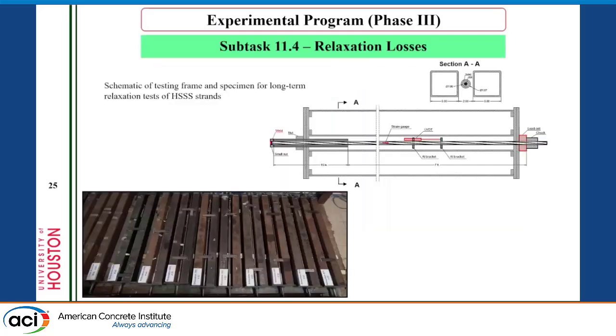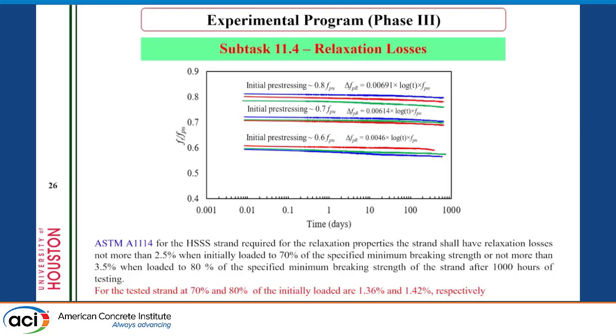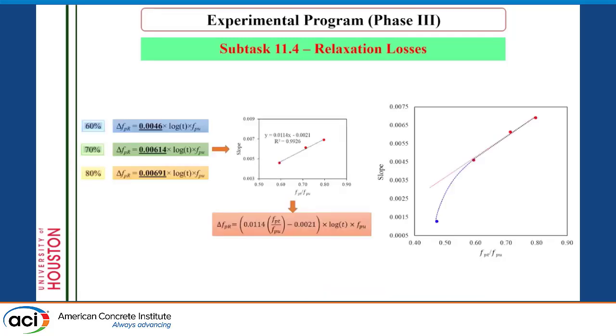Another topic is the relaxation. The same thing: we have to measure the relaxation to measure the losses. So we did the same thing. We tried to stress it at different stressing levels, 60, 70, 80%, and these tests have been running for 2 years as well. We tried to measure the losses for each strand and each stressing level, and after that we tried to correlate and get our relaxation losses.